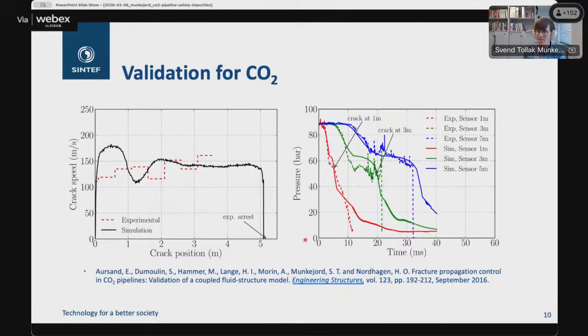To the right, you see pressure plotted as a function of time for different positions, 1, 3, and 5 meters from the original crack position. And you can see that there is reasonable agreement, although in some of the regions, for instance here, our calculation gives a higher pressure than measured. And one of the reasons for this is that in our model we assumed full thermodynamic equilibrium, which is likely not the case in reality. By the way, the vertical lines here are where the data acquisition system failed because the pipe was hauled out on the moor, so to say, because of the strong effect of the crack.